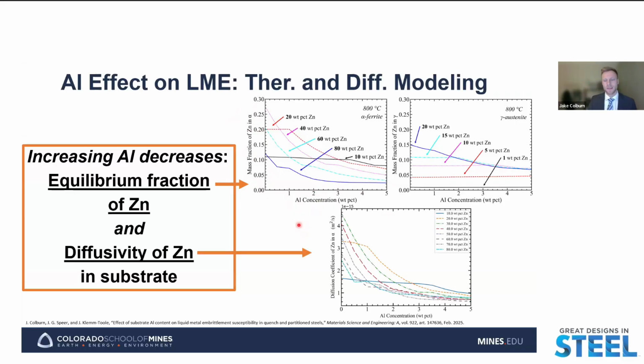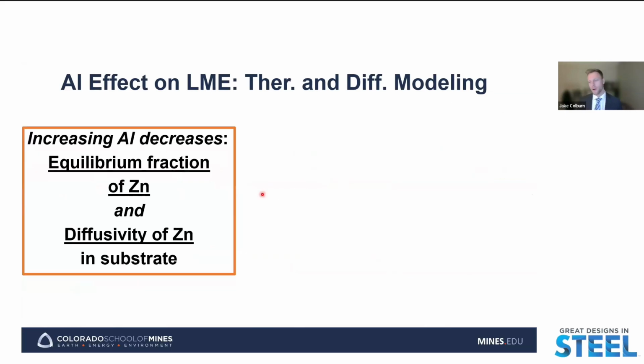But even more than that, we see that increasing aluminum concentration in the substrate also affects the diffusivity of zinc in the substrate, to where as we increase the aluminum concentration, again at different zinc contents in the substrate, we see the diffusion coefficient of zinc generally decreases. And so we could say that there is a general decrease in the diffusivity of zinc in the substrate with increasing aluminum content. And so with those two factors, if we're concerned with the diffusion flow of zinc into the substrate, that's where we can go back to Fick's first law, where we say that the flux of the diffusing component into another component is going to be equal to the product of the diffusivity of that diffusing component and the concentration gradient of that diffusing component.